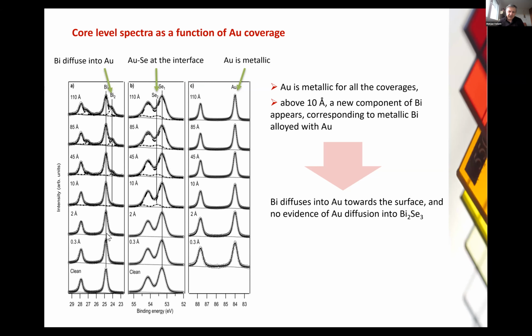understand what is happening. So what really is happening is that in this case, we do not get a redox reaction anymore. Gold is too noble, but something happens, and you know what happens? Do you remember when I said that we have a lot of defects in this structure? And the majority of defects are selenium vacancies. So in the system, we have an excess of bismuth, a slight excess of bismuth. And this bismuth moves from the bulk into the gold layer. And we get some kind of alloy, bismuth gold alloy. So there is no interaction, just slight diffusion of bismuth into the gold layer.